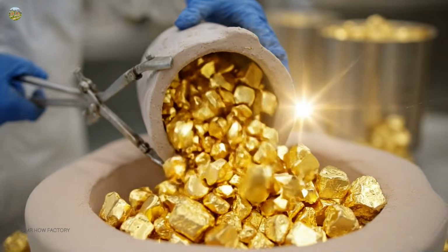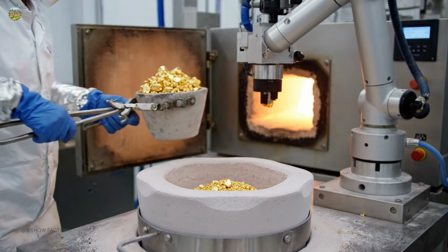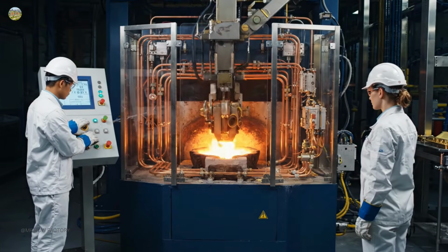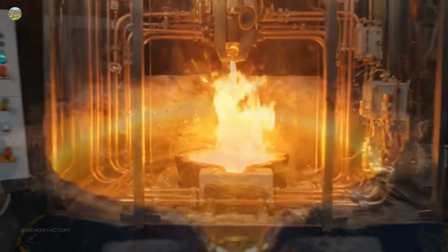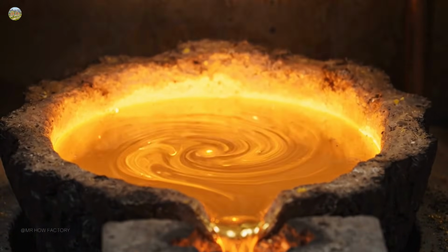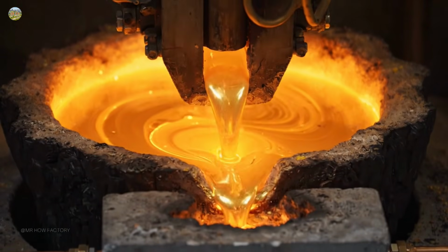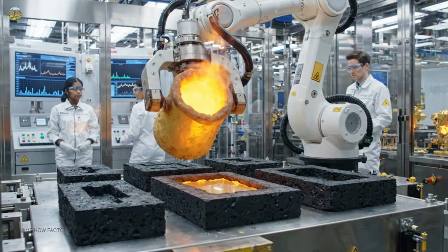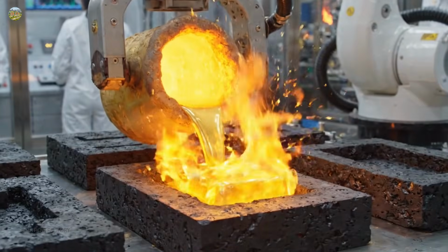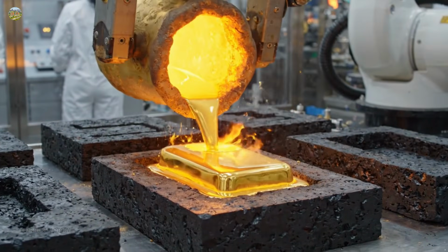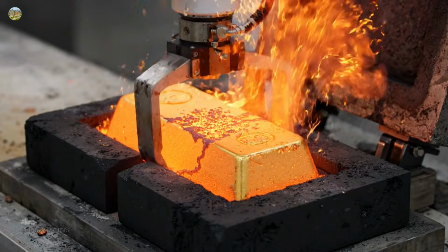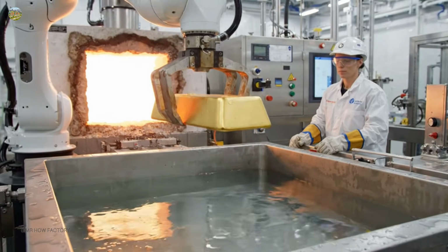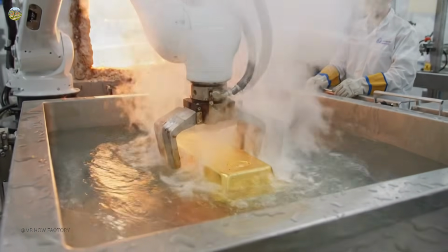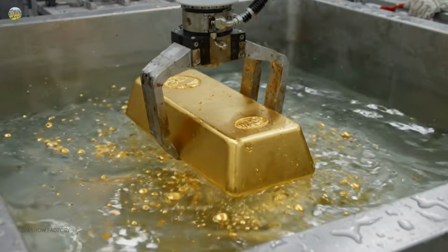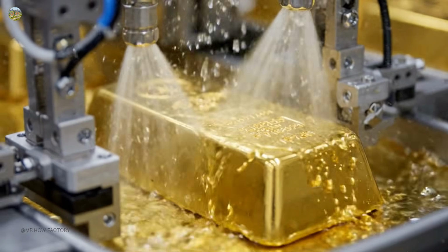Now comes the final stage, casting commercial gold bricks. Pure gold crystals are loaded into a clean induction furnace and heated to 1064 degrees Celsius until fully liquid. Robotic arms pour the glowing yellow liquid gold into graphite molds. The bar cools for a few seconds, turning solid red, and is then dunked into a cold water bath to cool down rapidly. The bar is then washed, cleaned, and dried.